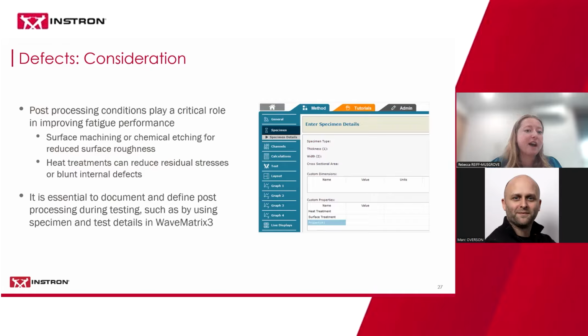And because of how critical a role these play, it's really essential to document and define the post-processing during testing. So there are different ways defined in standards by, for example, the ASTM community. But one simple way of doing this is just making sure it's written down with your test results, if your test results are completely dependent on the conditions. This is why we introduced specimen and test details into the Instron WaveMatrix 3 software, so people can write down in the properties their heat treatment, their surface treatment, any other treatments that might be critical to the testing results.